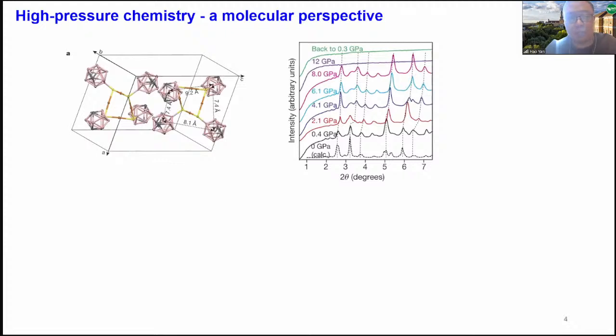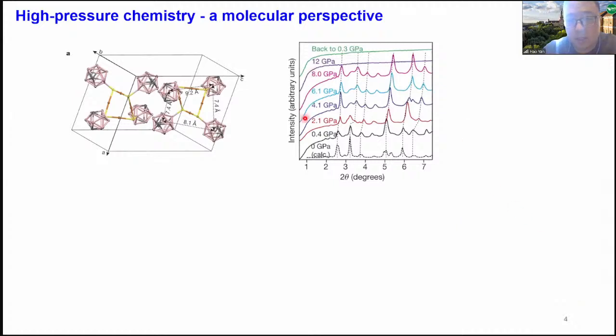Now, let me show you one example that I studied when I was a postdoc. We're looking at the high pressure behavior of this molecular compound - a tetrameric copper thiolate compound. On the right here, I'm showing you the pressure dependent X-ray diffraction pattern. And you see that it actually is pretty boring, right? You see all these peaks that are shifting to the right, which means that the unit cell is shrinking, and up to a certain pressure, the lattice collapses and everything turns into a flat line.